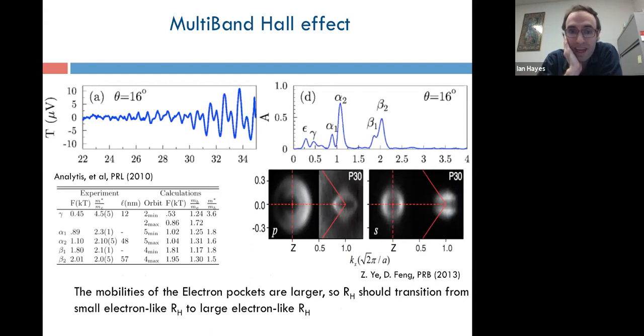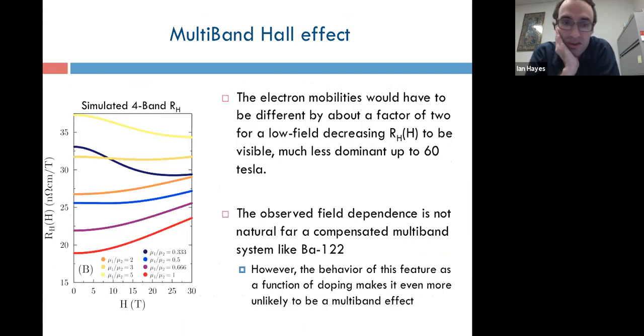of Barium-122. And in particular, in the phosphorus subseries, there's actually quantum oscillations that give us some idea about what the relative mobilities are on those two electron-like sheets, which dominate the Hall coefficient. And they are close to equal. They're within 50% or maybe 100%. And so that allows us to do just basic simulations and ask how much field dependence should we expect from that? And the answer is not very much. You still expect the hole and electron balance to dominate and for the Hall coefficient to simply increase with field.